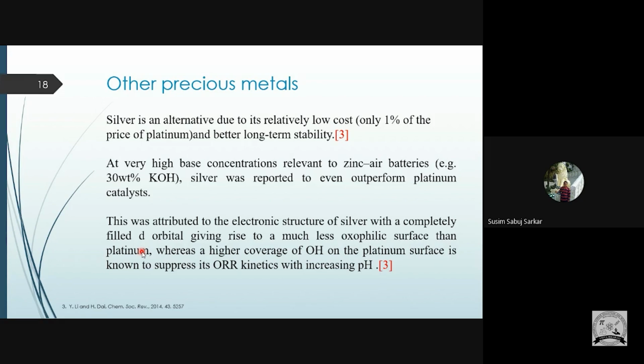On the other hand, in the case of platinum, the d orbital is not fully filled, there is some vacant space, so the OH can attach to the platinum, and it will ultimately affect the ORR kinetics, because we are using a highly alkaline medium in the zinc-air battery. So in that case the silver is outperforming the platinum, though in the normal graph the platinum has higher activity. But you have to remember that we are using it in a highly alkaline medium.